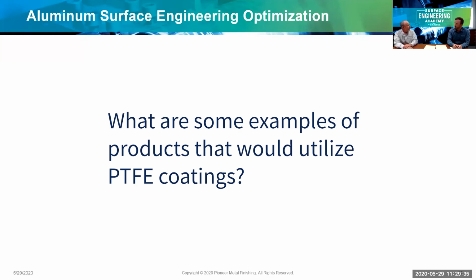So we were talking about anodizing. We have two different versions that can take this hard coating, specifically the type 3 anodizing, and impregnate the surface with PTFE. One version is the hard lube, which will provide the best wear and lubricity. And then we've also got the Tough coating, which provides great corrosion protection and lubricity. We also can, as I mentioned before, co-deposit the PTFE into electrolytic nickel coatings. And then you get the advantage of not only the slipperiness that comes from PTFE, but also the hardness of the electrolytic nickel coating for long wear. And we also offer direct PTFE coatings applied right onto the steel base. Sure, dry lube, for example.